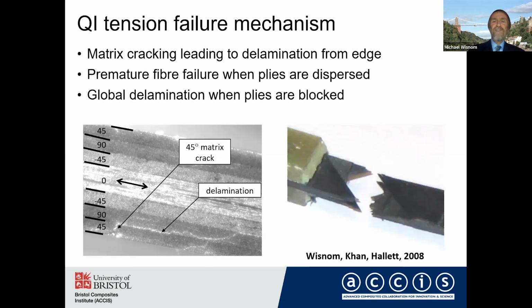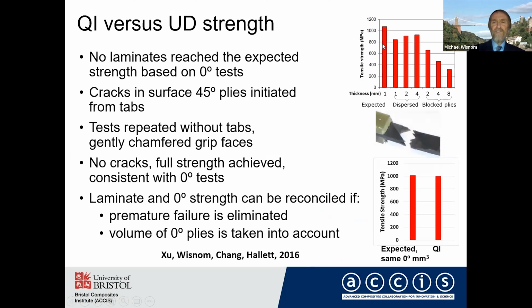So looking at that specimen, it looks like a gauge section failure. You see most of the failures at the edge, but my colleague Xiaodong Xu was working on the quasi-isotropic strengths, and he was skeptical about these results, so he went and dug out all these specimens and noticed that although it appears to be a gauge section failure, that 45-degree crack is starting at the tab. And one of the other things I showed on this graph here is that none of those specimens have reached the strength you'd expect on the basis of the unidirectional strength. So they're all below that failure because they've started prematurely.